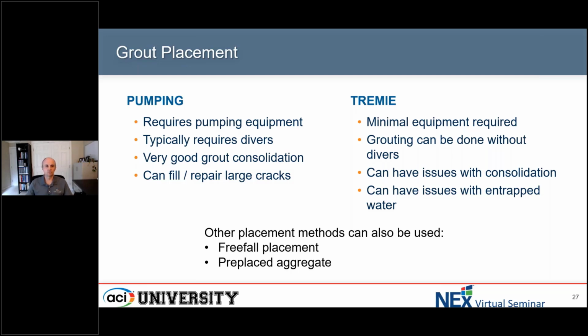There are applications where, instead of pumping the grout, you can tremie the grout, which just means dropping a grout hose between the jacket and the existing structure, down to the bottom of the encapsulation, and then essentially pouring grout into the form from the bottom up, allowing gravity to do its work and expunge the water out. Tremie grouting is a little less complicated, doesn't require as much horsepower out of the pumping equipment, and in some cases can be done without divers. But you can have issues with consolidation of the grout or with water still being entrapped in the encapsulation after the grout has been placed. So you can get less consolidation and less quality grout placement out of that type of method.